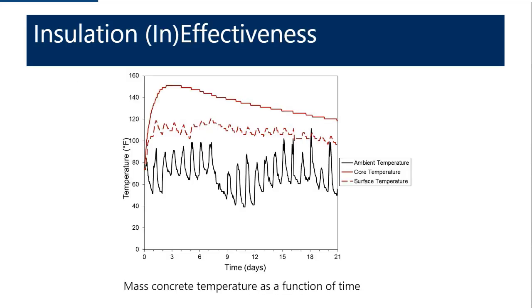So here's a graph that shows an example of an insulation being ineffective. In this particular case, they utilized an R5 insulation. What you'll notice is that the surface temperature sort of mimics and follows the ambient condition shown in black. The surface temperature is shown in the dashed line, and it follows the ambient conditions. While in this case the insulation was an R5, it was several years old and had worn down, had rips and tears in it, and as a result was no longer acting as an R5. It was acting like something less than that.